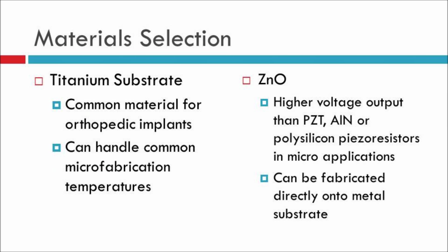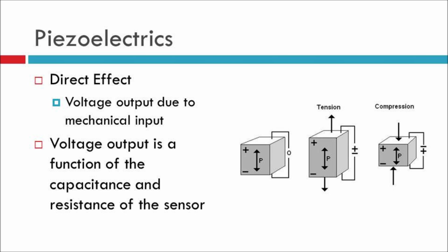For my materials, I have selected a titanium substrate, which is very common for orthopedic implants, and also can handle common microfabrication temperatures that are going to be used. For the piezoelectric, I'm using zinc oxide, which can actually be made to have a higher voltage output than PZT or aluminum nitride or polysilicon piezo resistors in micro applications. And another great benefit of zinc oxide is it can actually be fabricated directly onto the metal substrate.